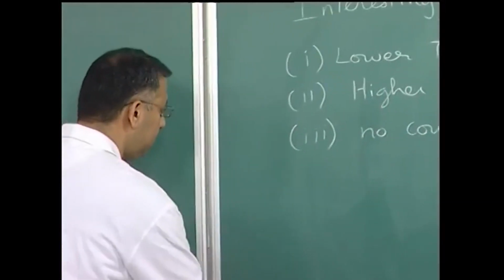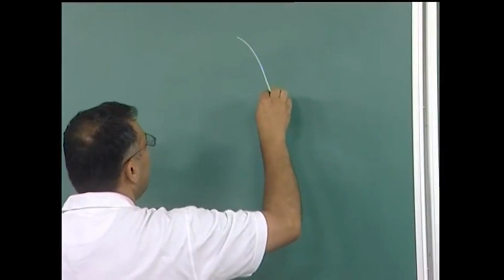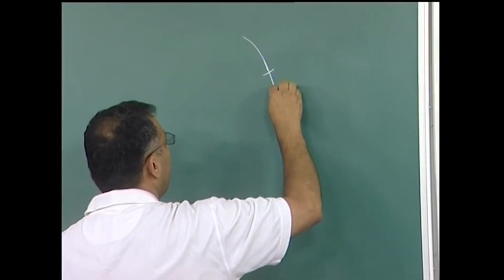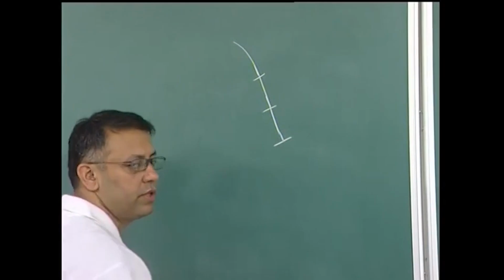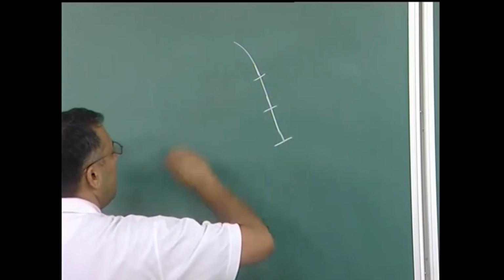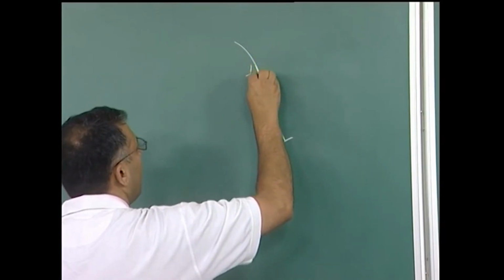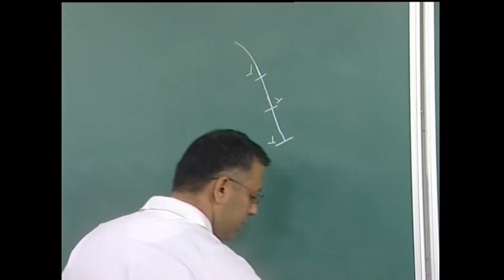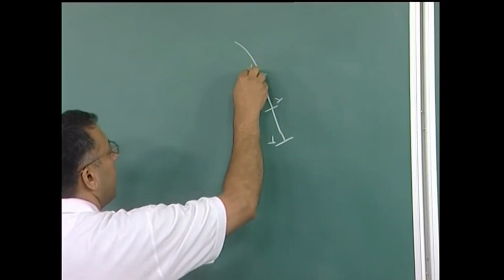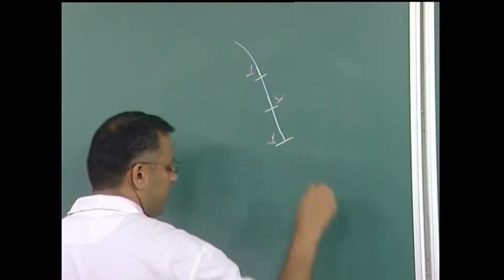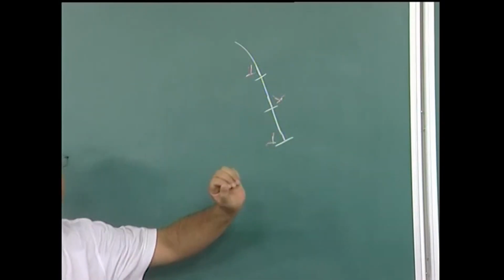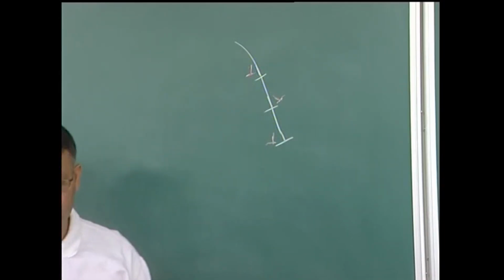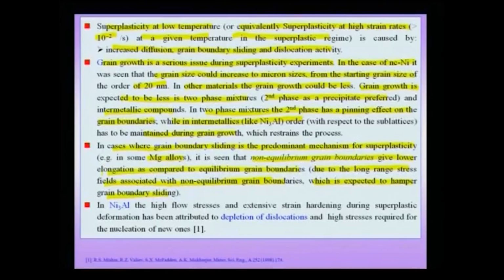So, you have a grain boundary, and this grain boundary itself, by the Read-Shockley model, may have certain dislocations which are the interfacial dislocations, or the grain boundary dislocations, but in addition to it this grain boundary may be associated with additional dislocations, and these additional dislocations which I am drawing in red give rise to a long range stress field for this grain boundary, because this array of dislocations does not have a long range stress field, while these red dislocations will give rise to a long range stress field, and due to these long range stress fields the non-equilibrium grain boundaries are expected to hamper grain boundary